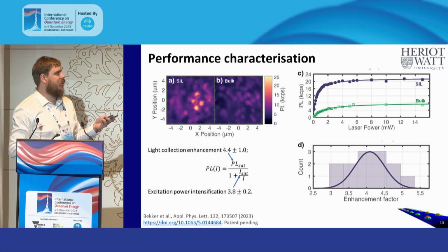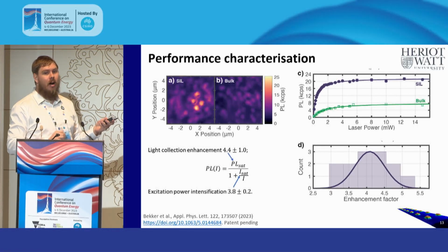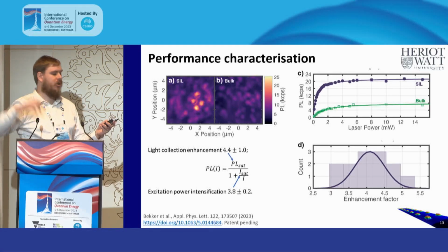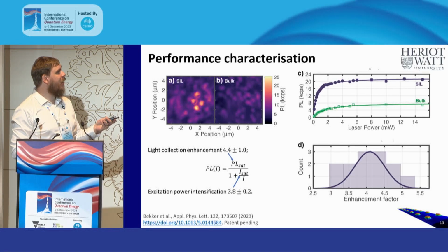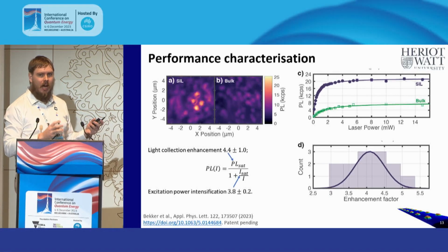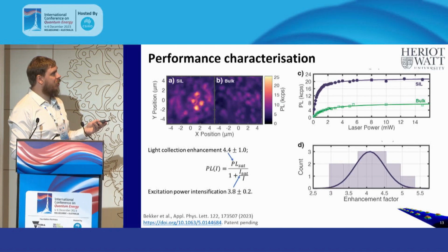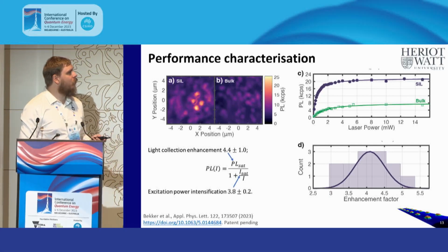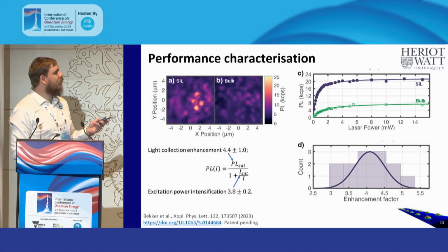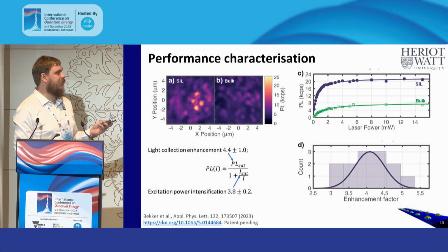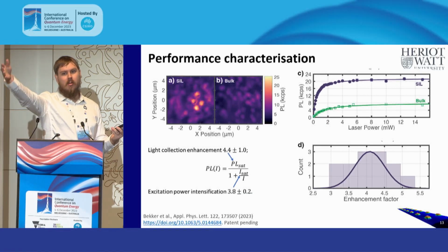And some of the bright spots here are actually two silicon vacancies nearby each other. Some of the darker spots are single vacancies where you've just knocked away a silicon atom. This here is the same photoluminescence map inside of a solid immersion lens. You can see these four images here that come up more brightly, because they're inside the lens. So here is just an example of what we call a saturation plot.